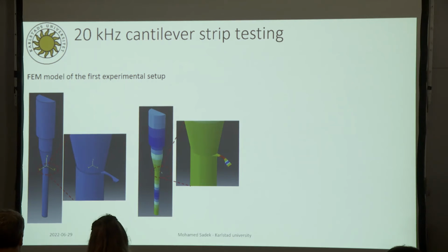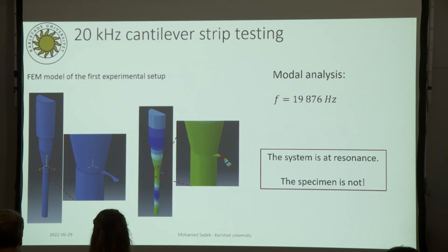Then we modeled the whole setup with the horn and the rod below the specimen to see the effects of that. We did a modal analysis, and we found out that the frequency is well within the ranges, but again, as I mentioned earlier, the system here will be at resonance, but not the specimen. The specimen will be forced to follow the system.